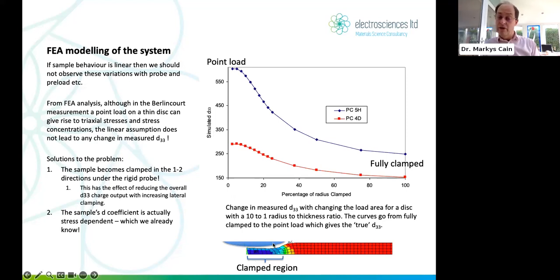Now, when we apply a load under this hemispherical domed electrode, that's not moving in X and Y, which means when it's in contact with the sample, especially if the sample's a thin film, then that part of the film is clamped. It's not able to move in X or Y. It wants to move in Z and generate a charge, but it can't move as much in Z as it wants to because its X and Y is clamped. Okay, this is a big issue in any thin film work, thin film piezo ferroelectrics. Everyone on this call probably knows that, but it's also an issue here. Therefore, this effect here of the d33 that you might measure as a function of how much you're clamping that piece of material. In other words, what's the region of stressed area of stress material?